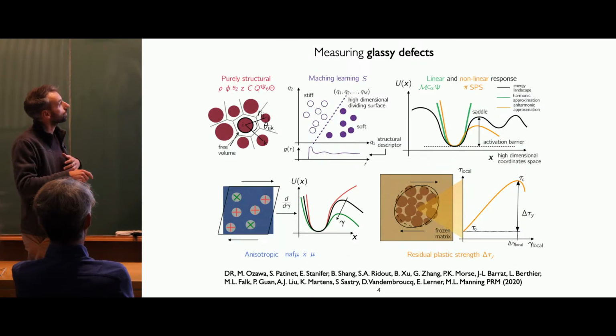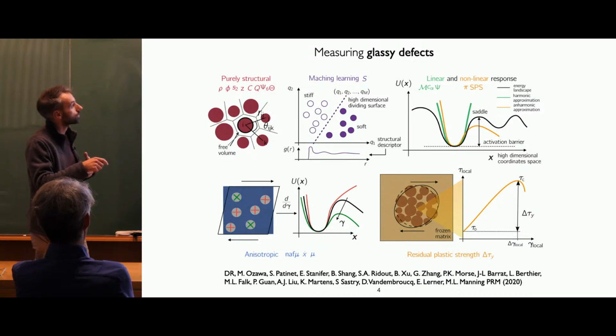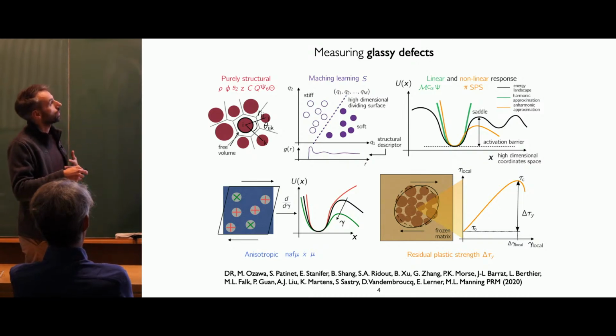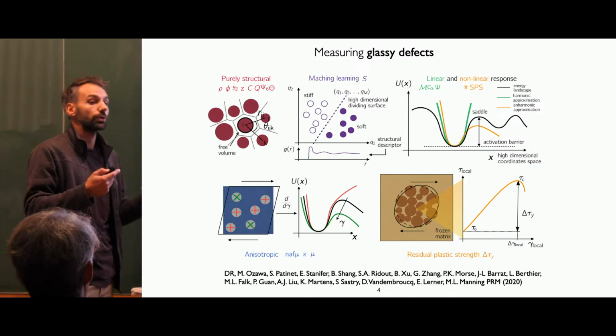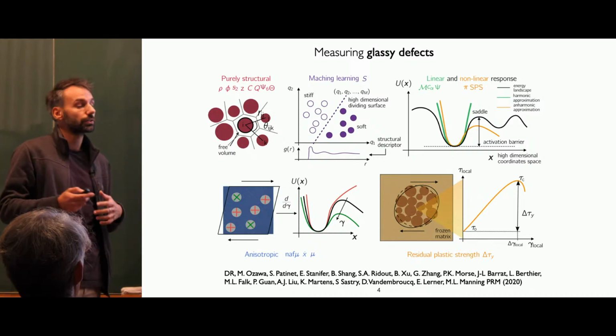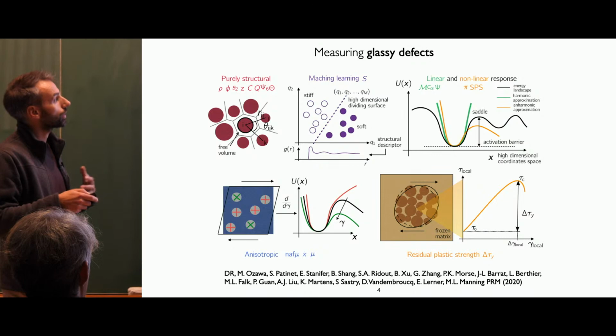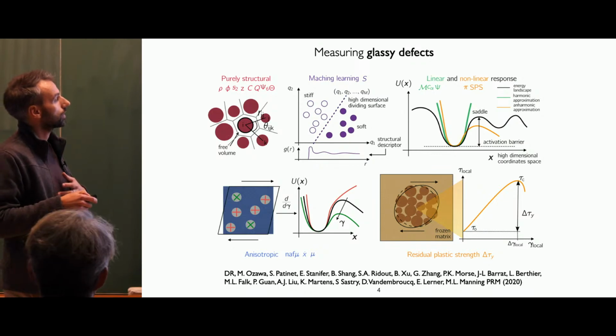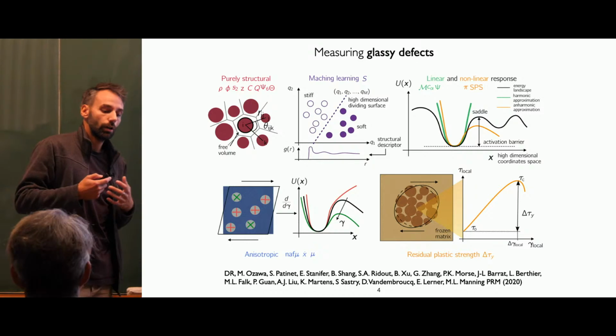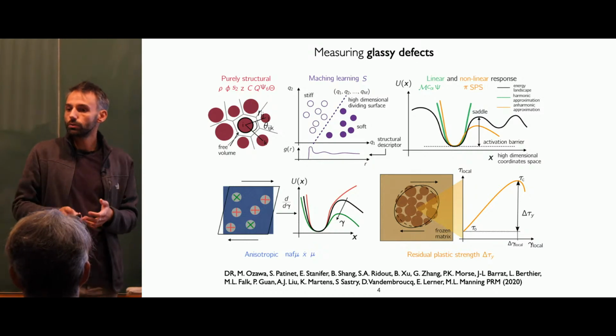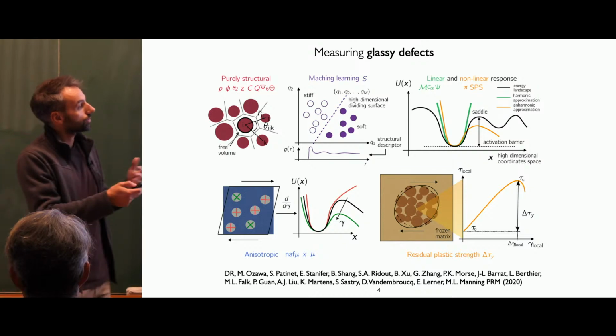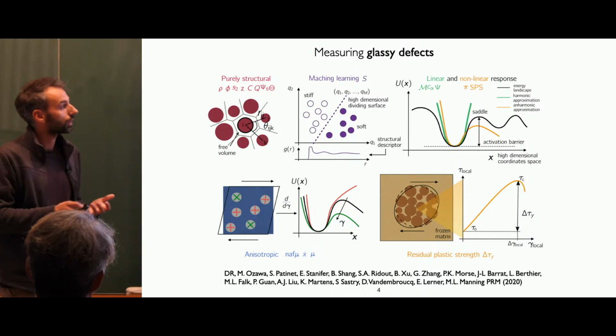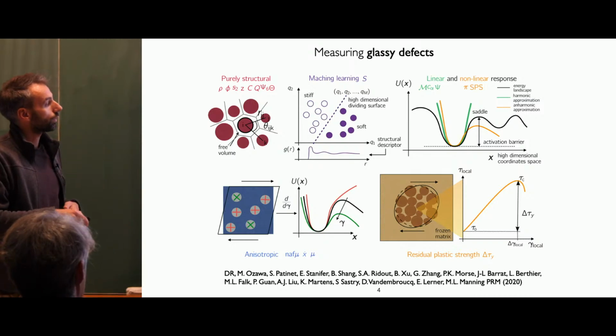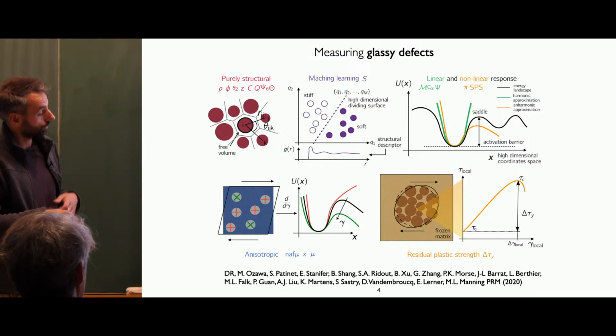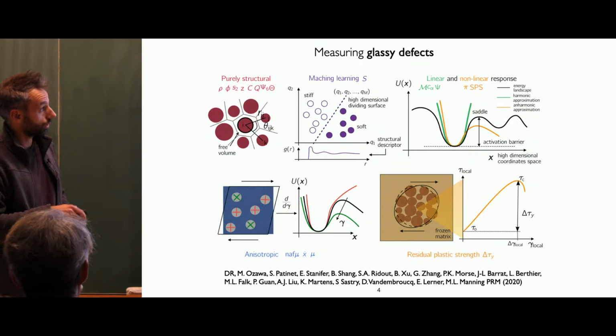You have already seen this morning a large variety of methods which are, for example, purely structural or machine learning based, but there are also communities that work on other types of methods which are not necessarily purely structural and also require interaction between particles. So I can base on the potential energy landscape of a glass some anisotropic indicator, for example the local shear modulus. And even things that are not local, where you really have to deform your system to get some information about heterogeneity, like the residual plastic strength, sometimes called the local yield stress.